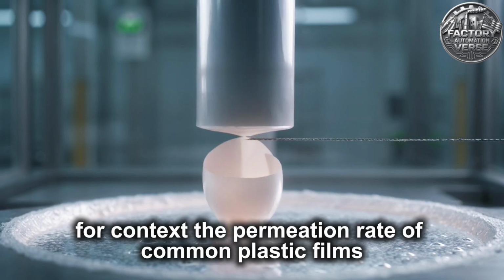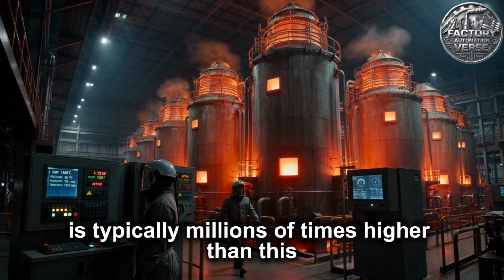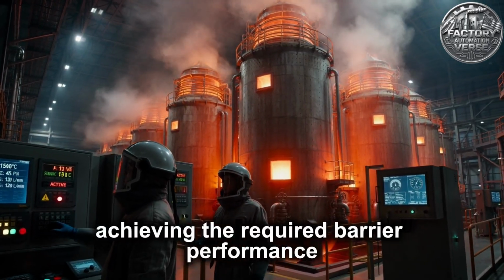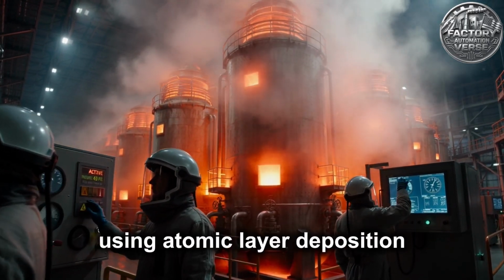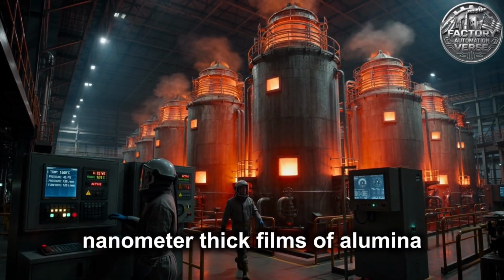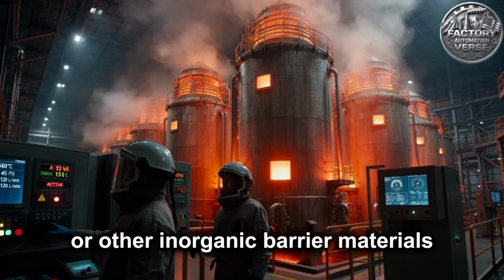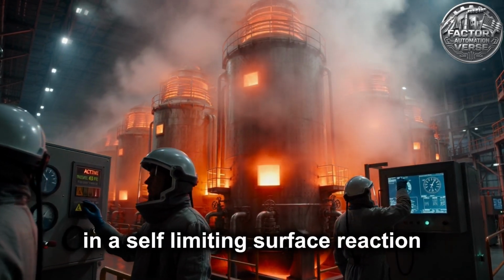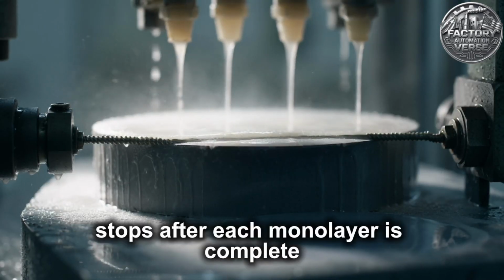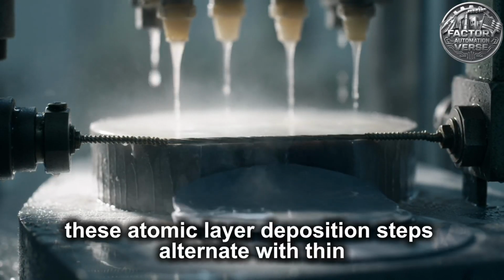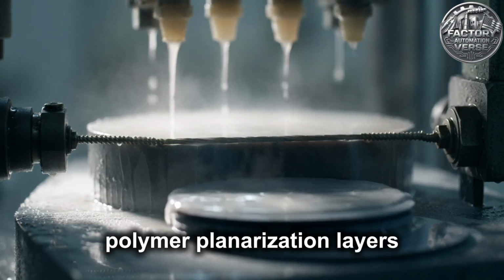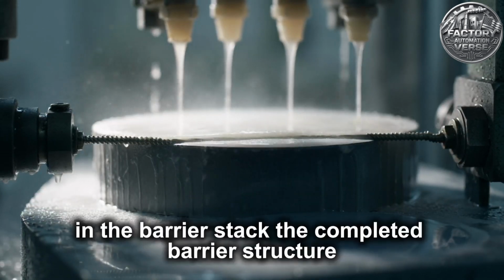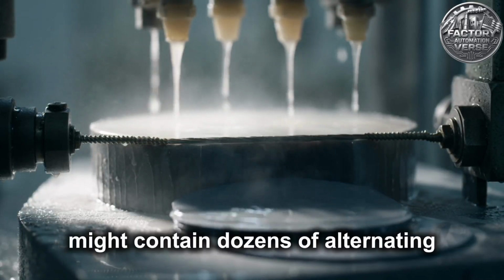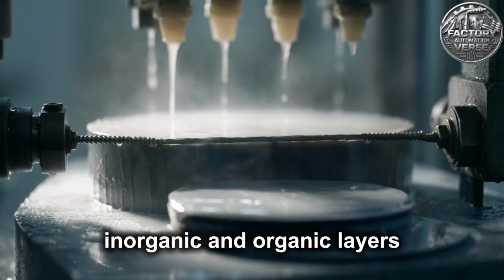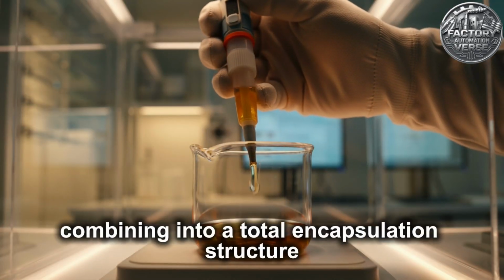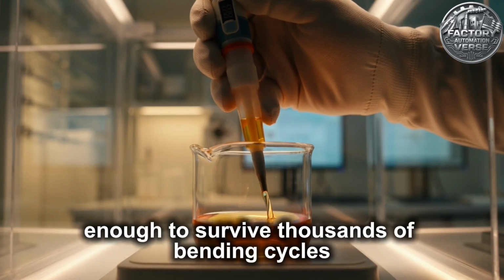For context, the permeation rate of common plastic films is typically millions of times higher than this. Achieving the required barrier performance requires multi-layer encapsulation systems using atomic layer deposition, a technique that builds nanometer-thick films of alumina or other inorganic barrier materials literally one atomic layer at a time, in a self-limiting surface reaction that automatically stops after each monolayer is complete. These atomic layer deposition steps alternate with thin polymer planarization layers to smooth any surface defects that could create pinholes in the barrier stack. The completed barrier structure might contain dozens of alternating inorganic and organic layers, each only a few nanometers thick, combining into a total encapsulation structure that is still flexible enough to survive thousands of bending cycles.